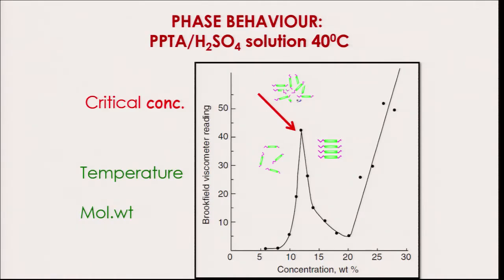So, for making the fiber, I would like to use the concentration where the processability is good, that means the viscosity is low and the concentration is high. So, in this particular case, you just look at about 18-20%, the viscosity is minimum, right. So, we choose a concentration of about 18 to 20% in this particular typical case for spinning, so that the processability is good and the solution is above the critical concentration.